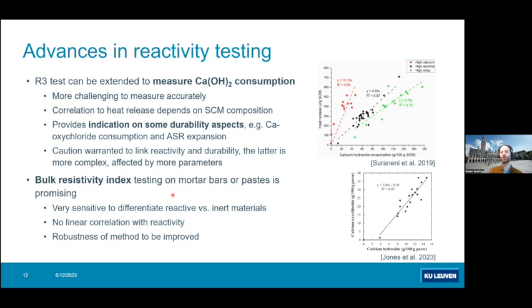Calcium hydroxide consumption can be interesting for some durability aspects which are particularly linked to calcium hydroxide presence, such as calcium oxychloride formation, where good correlations have been seen, and ASR expansion. Obviously, reactivity can give indications on durability, but it's not as easily linked as to compressive strength or other performance parameters. Durability depends on many different parameters and is in general more complex to understand. However, screening a filler material from a reactive material is still very valuable because we know that cements containing reactive SCMs are usually more durable than cements containing fillers.